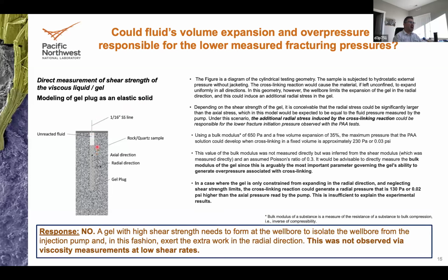And what we think will happen is that in the case when you have polymer, the CO2 will react with the polymer solution and form a kind of shell, or some sort of material that will have very low compressibility, but at the same time, since it's expanding in volume, it needs to have 2 things to be able to have a localized pressure that does not communicate to the pump. One is high shear strength, so the plug doesn't just get expelled from the wellbore. And second, a very high bulk modulus.